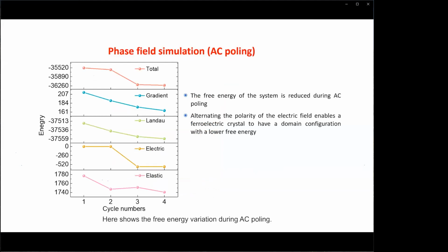Here shows the free energy variation during AC poling. We can see that the free energy of the system is reduced during AC electric field poling. This is because the energies arising from the discontinuity of polarization and strain around the domain walls drastically decrease as the domain wall density decreases. In other words, by alternating the polarity of the poling electric field, we can make a ferroelectric crystal achieve a domain configuration with much lower free energy. That is a domain structure with an enlarged domain size or reduced domain wall density.